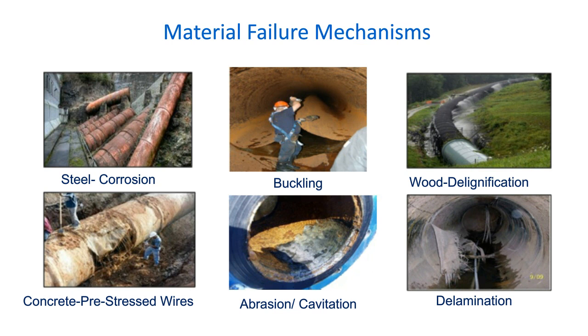Pre-stressed PCC pipe, you can kind of see a picture here, is the pre-stressed wires that actually keep the concrete in compression, have snapped, and that's through corrosion as well, abrasion or cavitation, as we talked about the inlets or the outlets of the Penstock pipes. We see a lot of abrasion or some areas cavitation. A lot of the abrasion is coming from sand and silt that's being abraded against the surface. And for FRP or sometimes repaired pipes, you can have delamination of the actual fiber or FRP cloth. So types of failure mechanisms.